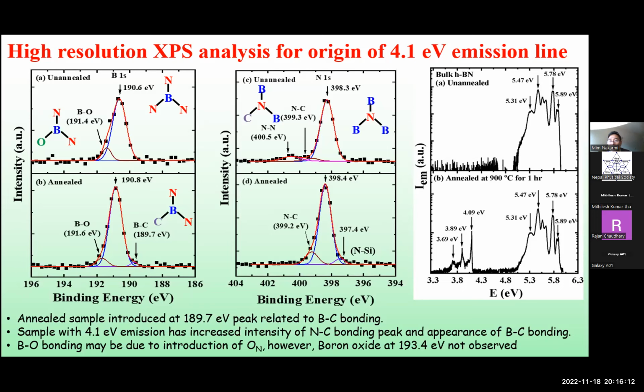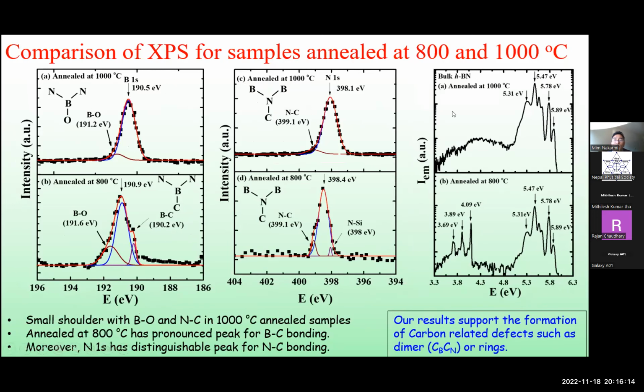And we also did more experiments with another sample. The previous comparison was one sample not annealed and one annealed. Here both are annealed, but one is annealed at a very high temperature, and high temperature annealing also does not give any 4.1 emission. So we also compared those two. Similarly here, it also has an additional peak, which is the bonding between carbon and boron, very clear and pronounced.